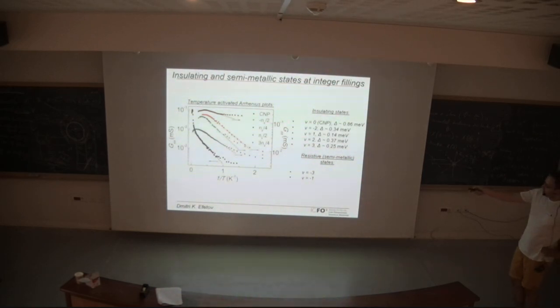Indeed, what we do for this is we sit at the integer filling, we measure conductance as a function of temperature, and we plot it against inverse temperature. These straight lines here are exponential fits for the temperature activated gaps. And we can really extract insulating states at many fillings, so at -2, at +1, 2, 3, and at the charge neutrality point, 0. They all have varying sizes of insulating gaps, but these gaps are all below 1 meV, so in principle they're very small.